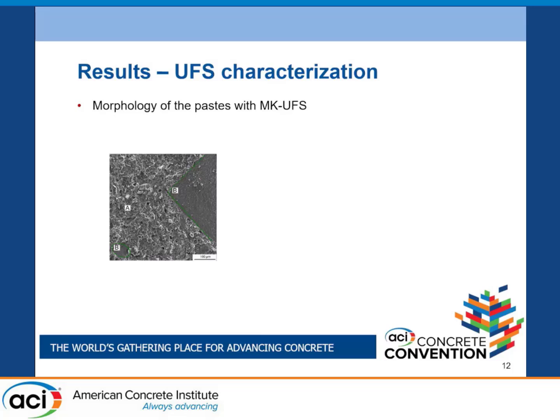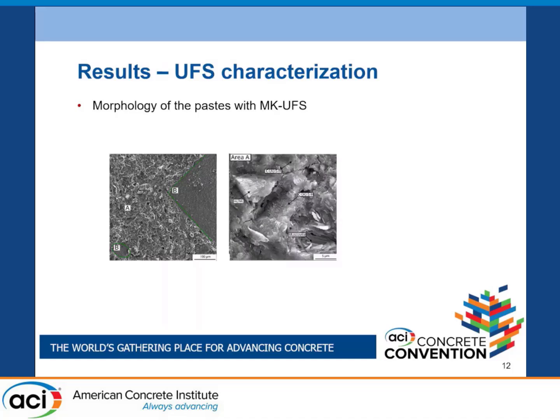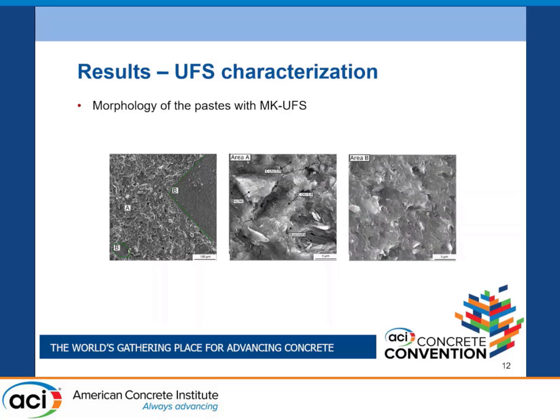Now I want to present some SEM images from the paste prepared with the metakaolin and UFS. In these SEM images, we saw almost two different microstructures, area A and area B. Area A was a typical microstructure that we also saw in the sample with metakaolin and slag before grinding. So some minerals in the clay, muscovite, or different morphology of CSH, we saw in area A. But area B was mainly a CSH structure, a very compact, homogeneous structure.